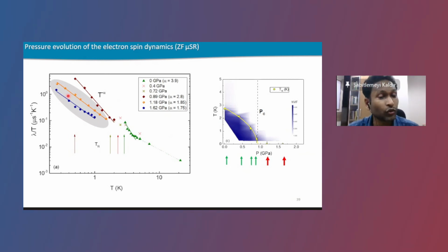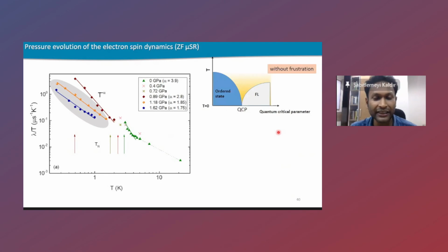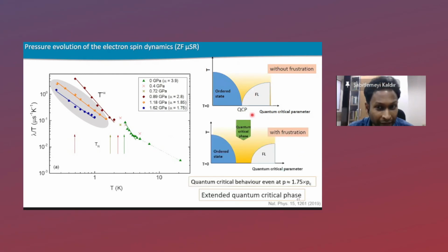That tells you that you have critical fluctuations, quantum critical fluctuations, that are still surviving much higher than the quantum critical point. And that tells us that this is the generic phase diagram that I have discussed. That might be associated with the fact that, because of the incorporation of frustration, we have not only a quantum critical point, but rather an extended quantum critical phase in this particular system. So we have got the microscopic evidence of having an extended quantum critical phase in this system.